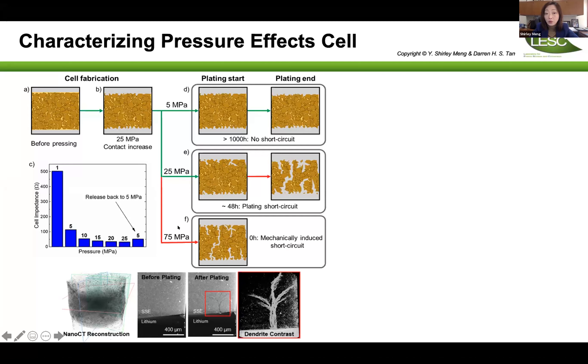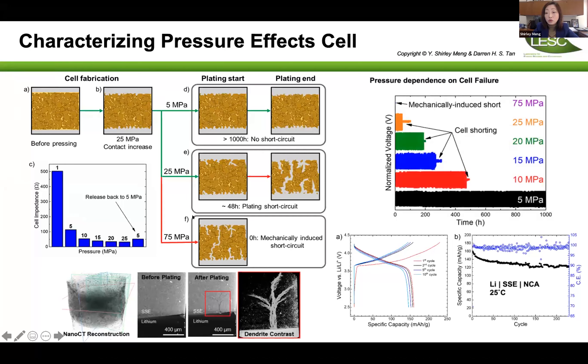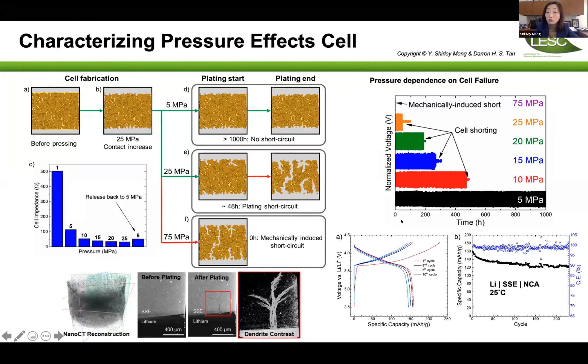My postdoc Jean-Marie spent considerable time thinking about the effect of pressure on lithium metal. Since lithium metal is viscoplastic, the pressure actually needs to be lowered to enable room-temperature cycling of lithium metal. As Professor Sun showed, our critical current density is also very low — only 0.1 mA/cm². There's still a long way to go to optimize solid-state cells, but good progress has been made. Since the anode lithium is very soft and the cathode oxide is very hard, understanding how to mechanically make them compatible — with pressure as an important tunable parameter — is key.